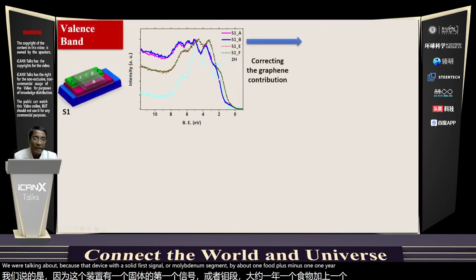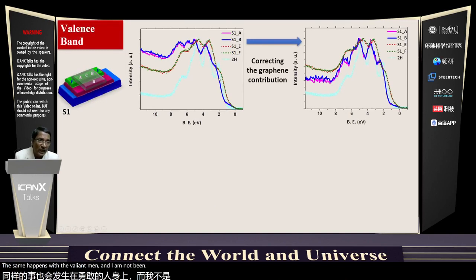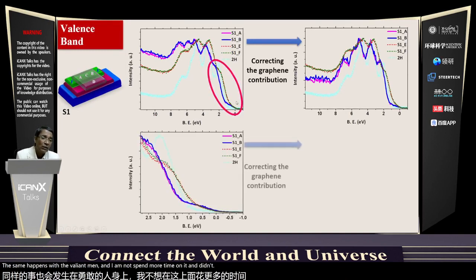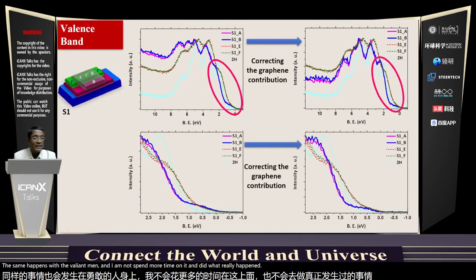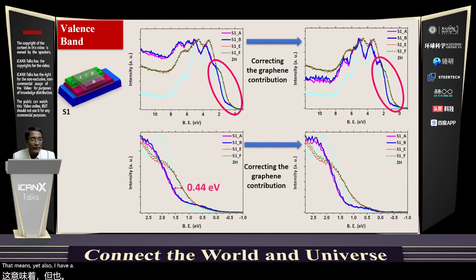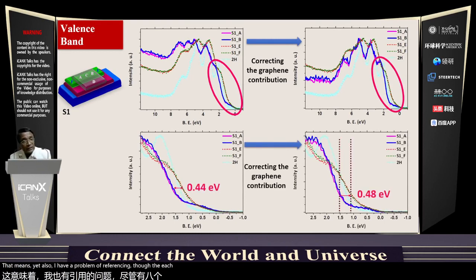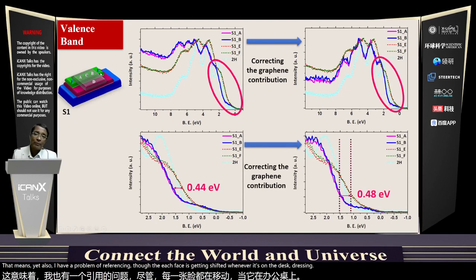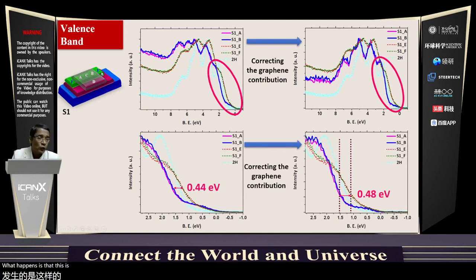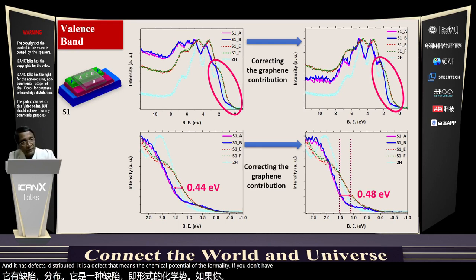The same happens with the valence band, and I'll not spend more time on it and tell you what really is happening. That means here also I have a problem of referencing, though the H phase is getting shifted whenever it's under the graphene. What happens is that this MoS2 H phase is a wide bandgap insulator. And it has defects distributed. It is a defect that pins the chemical potential, or the Fermi energy, if you don't have the graphene on top.